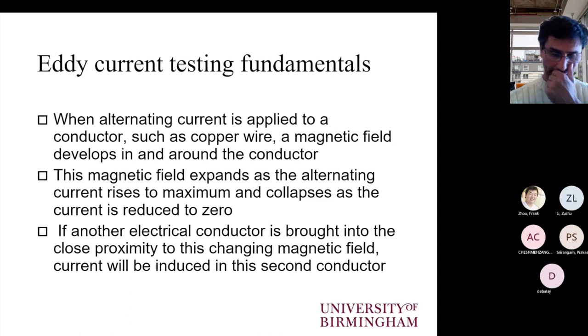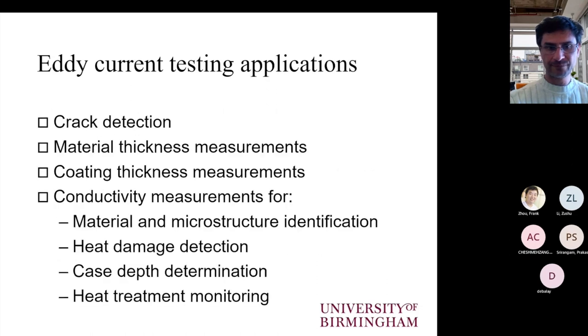Of course, very important in eddy-current testing is the distance from the test piece. So we have to ensure that the inspection is taking place at a steady liftoff and preferably as close as possible to the test piece. Usually no more than 1 millimeter, maybe 2 millimeters max. Above that, the response is reduced quite a lot, and of course, that results in a very poor signal to noise ratio.